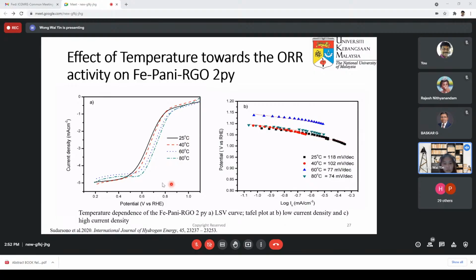So in this half cell test, when we manipulate the cell temperature, with increase in temperature we can see that the onset potential shifts to the positive direction, showing that at a higher temperature the kinetics of the catalyst is better. You can see from this Tafel plot that from low temperature to high temperature, there's a reduction in the Tafel slope. The ideal value, comparable to the Pt/C, is 60 millivolt per decade. So at 80 degrees Celsius it is near the desired value.